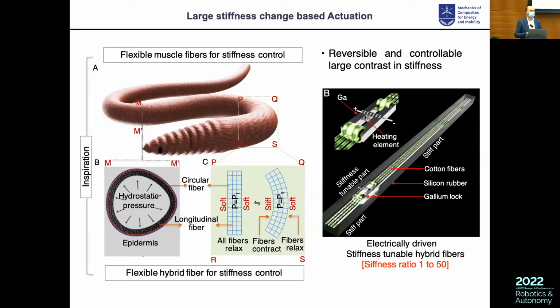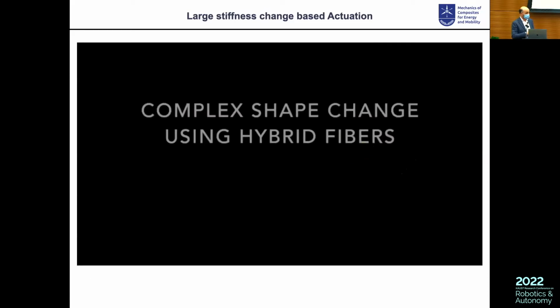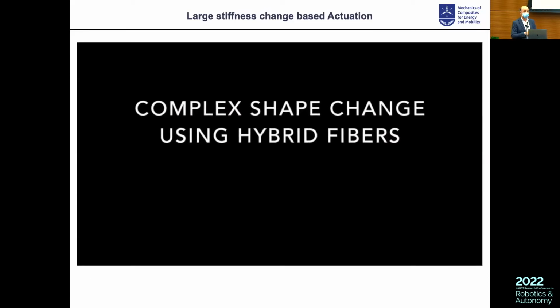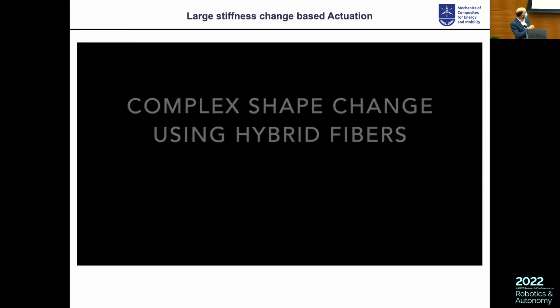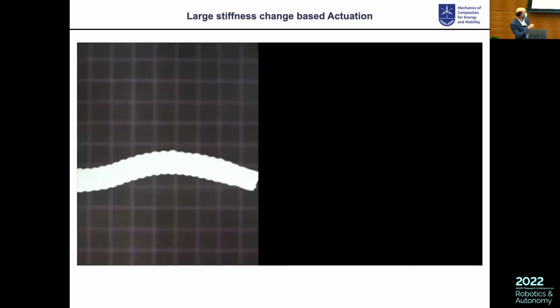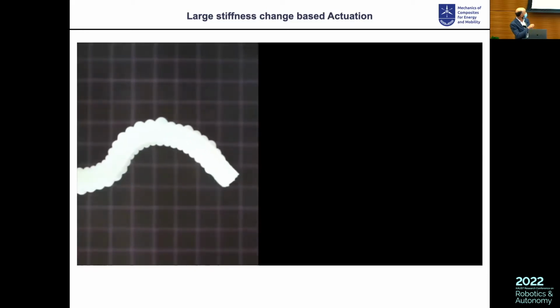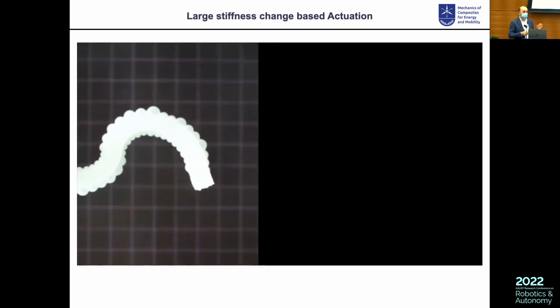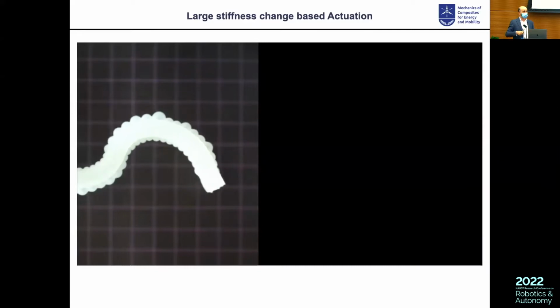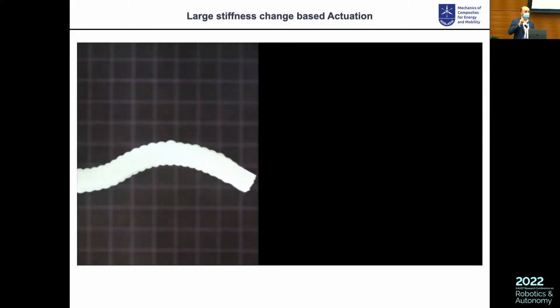It's based on gallium. This kind of fiber can be either very stiff or very soft when you induce the melting of the gallium. If you put this inside the skin of this kind of system, you have some fibers in the skin, and depending on the point, you activate or not the melting of these fibers. Then you can control the stiffness and make a distribution of stiffness in your robots, and change the shape just by controlling this.